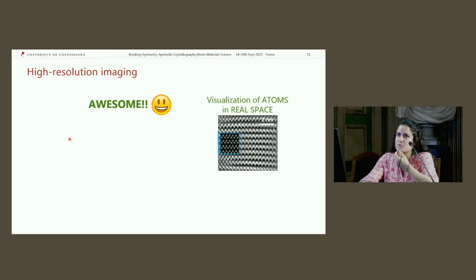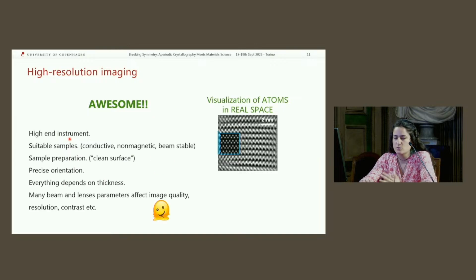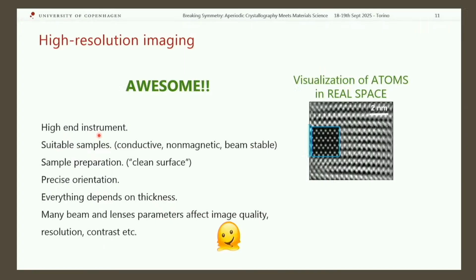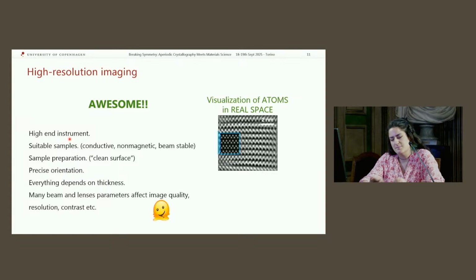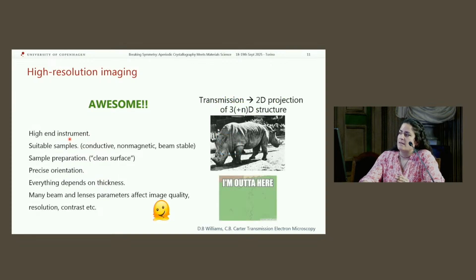But of course, what I showed you before is an exceptional result. So we need to have a very high-end instrument, a very good control of the conditions, and the beam, everything. The sample must be very smooth, very flat, very perfect, very clean. So everything must be controlled to a high level. But let's say we have the best instrument, the best sample, and also the best microscopist. Still, what we are seeing is a 2D projection of at least a 3D structure, because we are working in transmission mode. So this, yes, is a real image in real space, but it can be difficult to interpret.